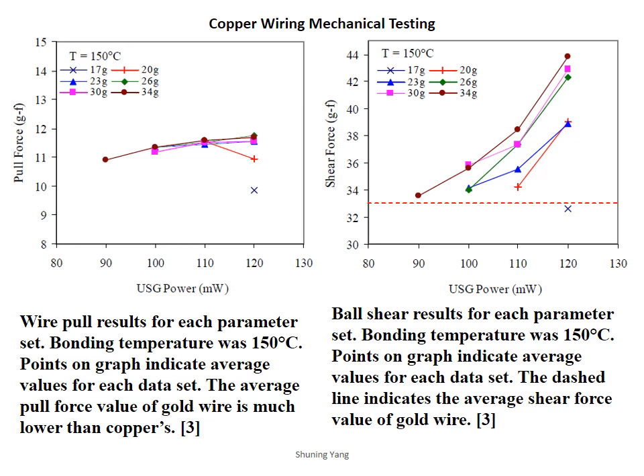The right image indicates ball shear results for each parameter set. Bonding temperature was 150 degrees centigrade. Points on the graph indicate average values for each data set. The dashed line indicates the average shear force value of gold wire. We can see that under the conditions of the same temperature, with different sets of bond force applied and ultrasonic power, the copper wire can bear higher pull and shear force than gold wire. It proves copper wire has a much better mechanical property than gold wire.